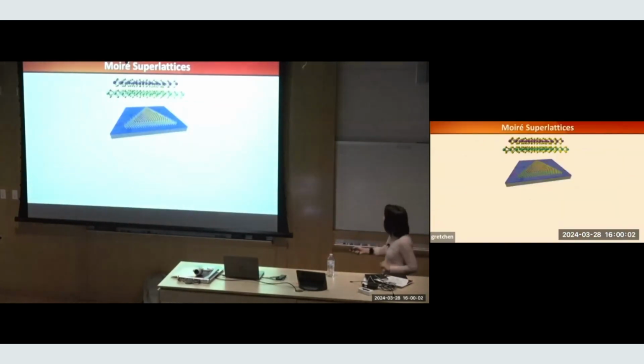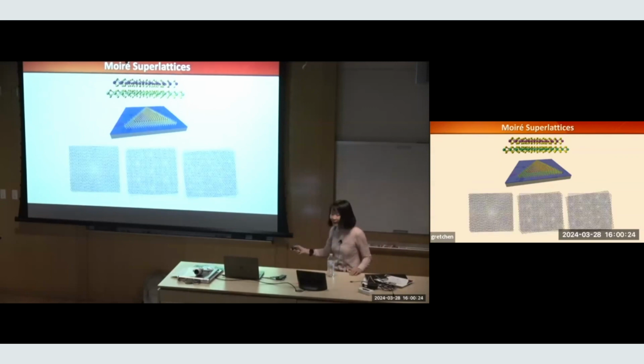But now you can build a Moiré superlattice by simply taking two layers. And because the layers have weak van der Waals force between them, you can now rotate them. If you're growing gallium arsenide based quantum wells, each layer has to be epitaxially matched. But these materials don't have that constraint. You can just choose to twist the angle. And now I have this superlattice developed in the plane. The larger the angle, the smaller the superlattice.